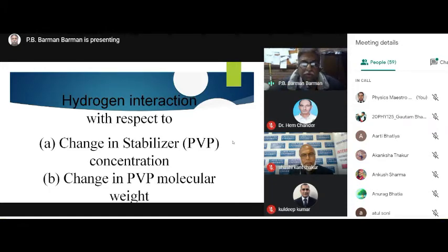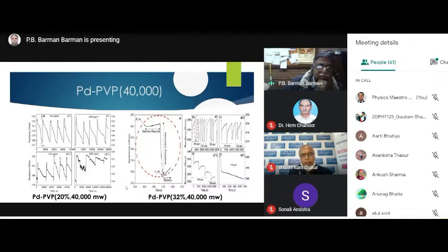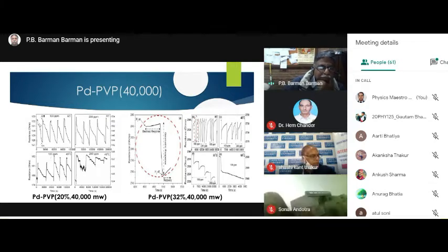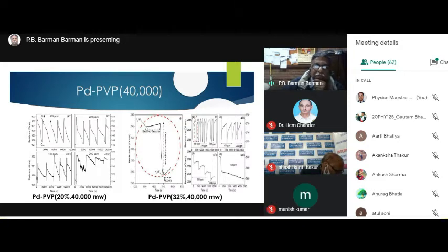So the hydrogen interaction with respect to the change in stabilization, and of course the change in PVP molecular weight - recently I showed the 40,000 molecular weight of the PVP. Now we can see here, let me zoom into that. Initially, this is the time and this is the resistance - initially there is an increase in resistance. I hope you remember that when hydrogen initially interacts with my palladium, palladium hydride is formed, which is practically responsible for the low conductivity or increase in resistivity.